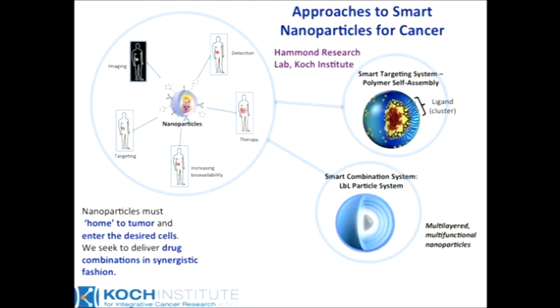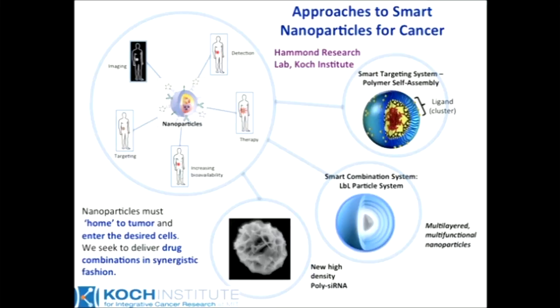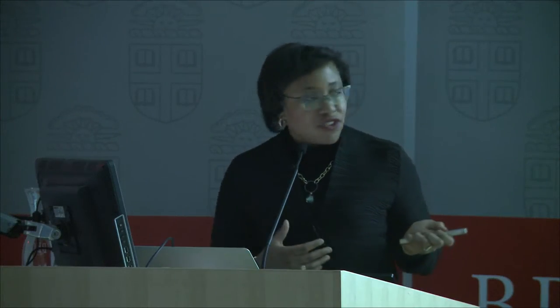And we use polymer chemistry to actually make these molecules. And the second that I'll describe to you is a combination system. It actually takes advantage of the fact that we can use a method called layer-by-layer assembly, which is an electrostatic assembly process. I'll describe to you in more detail soon. But it allows us to wrap molecular layers around a nanoparticle. The nanoparticle itself can contain a drug, and these wrapped layers can actually contain a second drug, and ultimately an outer layer which gives us the stealth and the ligand targeting that we want.